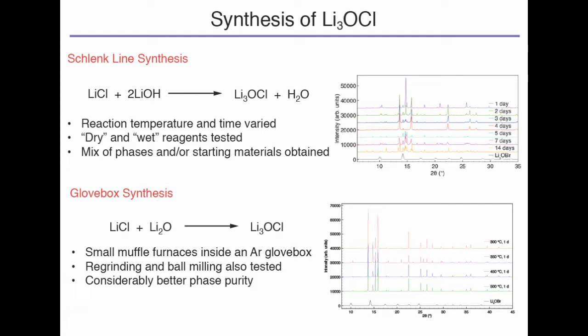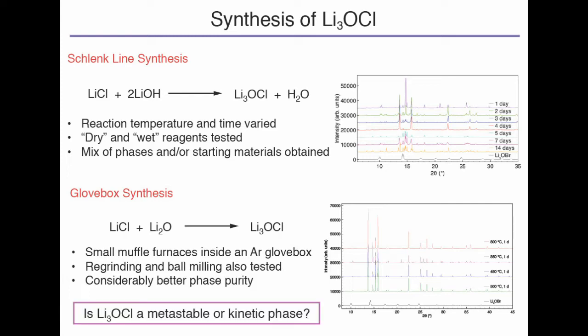Now again, we tried lots of different temperatures, different times, lots of different variables for reaction conditions. And in some cases, we did manage to produce small amounts of the Li3OCl, but nothing like the quantities that had been reported in that paper. So at this point, we started to think, can you actually make this phase? Does it really exist, or did they lie in their paper? So it made us think, is it actually more like a metastable or kinetic phase, i.e. something that can't be isolated in the bulk?